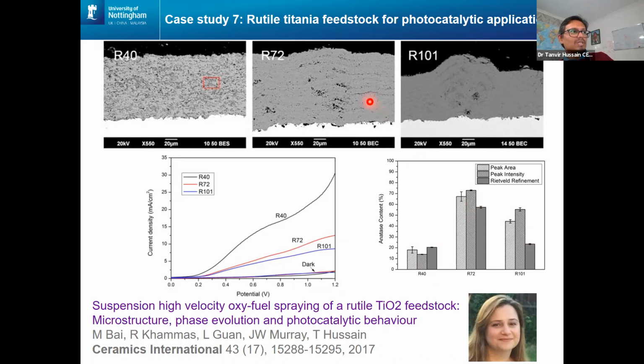That's one thing worth remembering, because titania is really great because it can react with UV light and it can break down surface contamination, and it's also used as a self-cleaning coating. But the ratio of anatase to rutile is quite critical in these coatings, and there's a lot of study out there where the argument is still going on about what's the optimum anatase to rutile ratio. And that's what we're doing. We're measuring current density versus potential of these three coatings under artificial light to figure out what would be an ideal composition here.